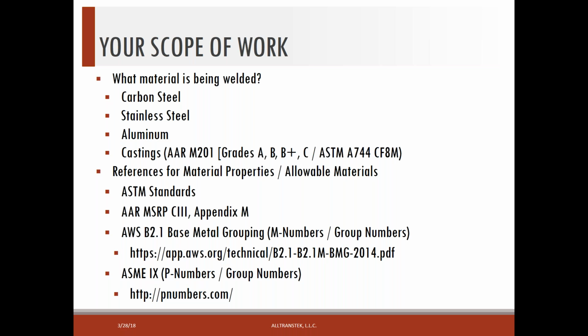If we have notch toughness properties or requirements imposed on the weld procedure, then the grouping has to be further limited. It can't just be an M1 group. We have to look at the group number. And so if I qualify a procedure without notch toughness and it's an M1 grouping or a P1 grouping, then I should be able to use that procedure for welding any M1 and any P1 material together.